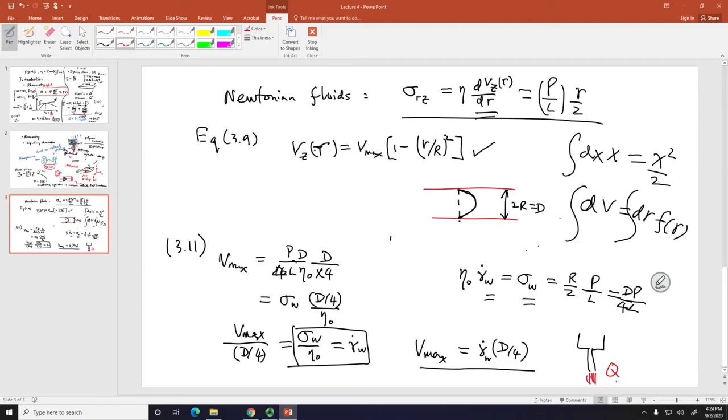It turns out that's a very measurable quantity. In fact, we have a rheometer that one day we can go to our lab and see, if you need. Basically, at every given moment, how much material is coming out that has a certain density. So if you weigh your material with the density known, you know how much material per unit volume is coming out. And that's an accessible quantity that we need to use all the time.